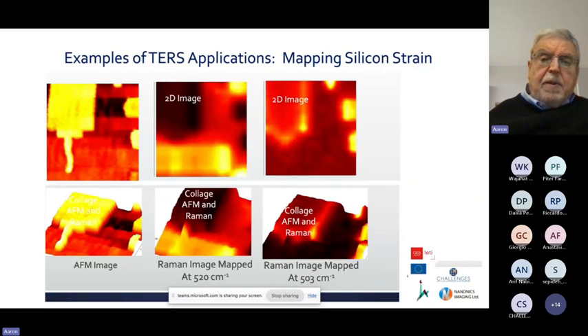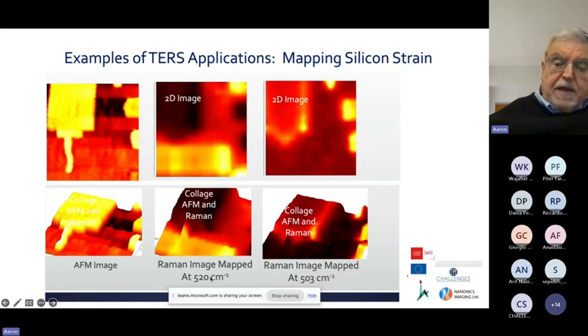This is an example of imaging of strained silicon. It's not done with this system, but I'm including it because it shows you the potential for the future. These are 2D images, and this is a 3D image, and it depends on the wave number of the band. If it's at 520 wave numbers, which is of course silicon, then you see this contrast. These are collages of the intensity of the Raman with the 3D. And this is 503 wave numbers, which is a sample we got from an industrial place, which allowed us to use it. I've never seen such a low strain silicon vibrational frequency. But you can see that the distribution is totally different depending on whether you're looking at silicon or strained silicon.